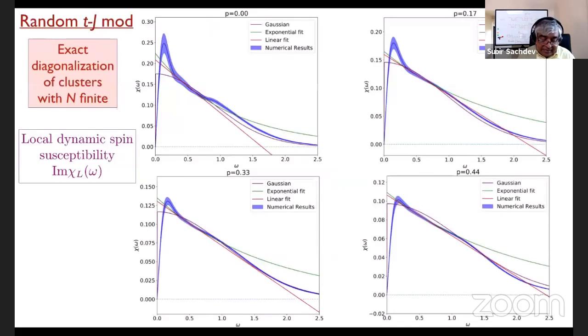So this is the same local spin susceptibility I showed you earlier, at p equals 0, at zero doping. And this was the spin glass peak that you saw. What we expect very generally, if you have SYK physics, is that there will be a linear omega term here. In the paper of Rosenberg et al., they've taken a Gaussian fit, which we think is not well motivated. But if you take the linear omega term, then you would say it's only this region above the linear fit that's spin glass order. So anyway, there's some ambiguity in how you estimate the spin glass moment associated with this little bump. Our procedure is somewhat different from Rosenberg et al. here.